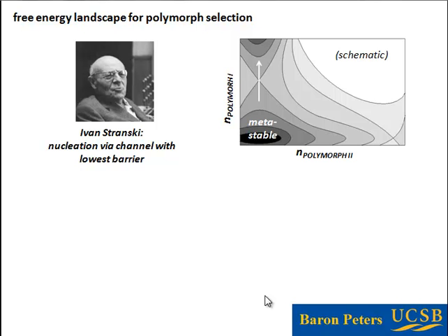And we know that this is actually not the correct story, because we can sprinkle a little bit of pixie dust into a solution and change which polymorph comes out, right? For example, a surfactant or salt or acid or something like that. And it doesn't take very much. You just slightly change the pH or the surface tension on those critical nuclei, and you can change which of the polymorphs you're going to make.